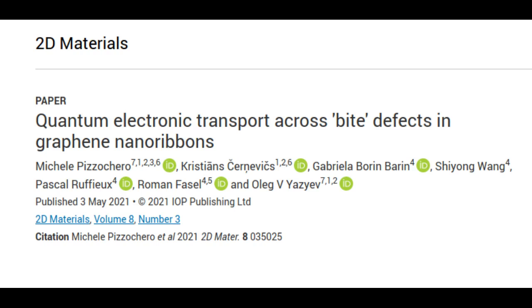The researchers then used first principles calculations to explore the effect of such defects on quantum charge transport, finding that these imperfections significantly disturbed it at the band edges by reducing conductance. These theoretical findings are then generalized to wider nanoribbons in a systematic manner, allowing the researchers to establish practical guidelines for minimizing the detrimental role of these defects on charge transport, an instrumental step towards the realization of novel carbon-based electronic devices.